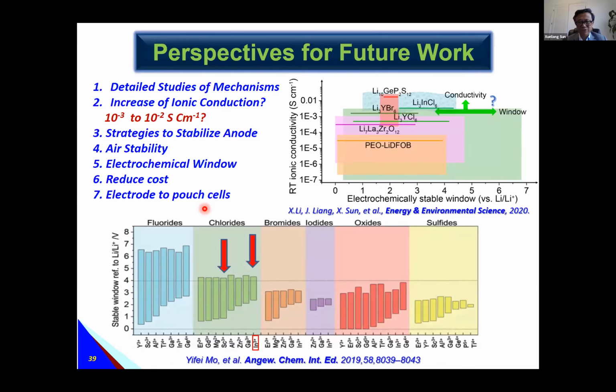So I'd like to thank Yifei Mo's group. Here they have a calculation to see what is the right direction. Now we see the indium chloride actually synthesized. If we talk about the window, here it is not very wide. And also recently we have scandium here, relatively wider. But a good system is fluoride, highlighted fluoride. You can see that for the cathode it is higher, up to 6, and the lower limit is close to lithium. So that means fluoride is a good direction, but we know it's a big challenge because it's hard to get a very high ionic conductivity.